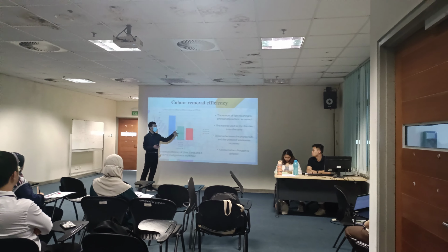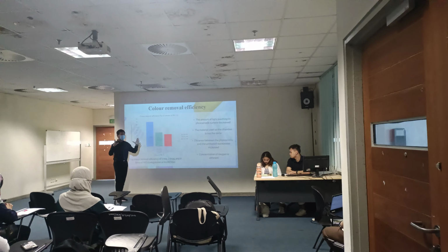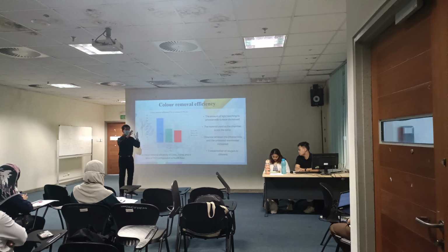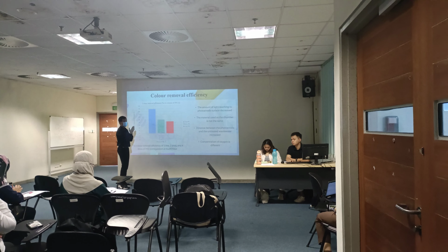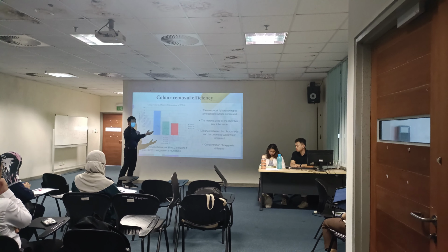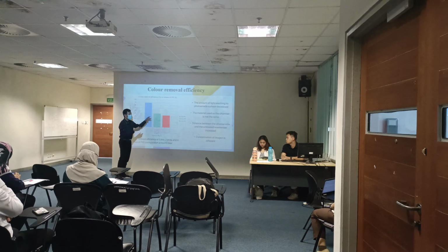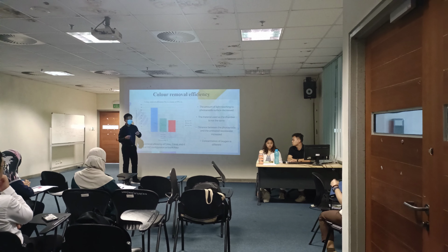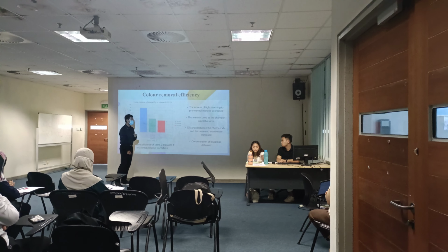The distance between the photoanode and the untreated wastewater has also increased because the size of the PFC chamber has increased. So the furthest distance between the untreated wastewater and the photoanode surface, where the formation of hydroxyl radicals occurs, has increased. And the PFC system is in stationary conditions, which means it solely depends on the diffusion of water to move the hydroxyl radicals to reach the untreated wastewater.